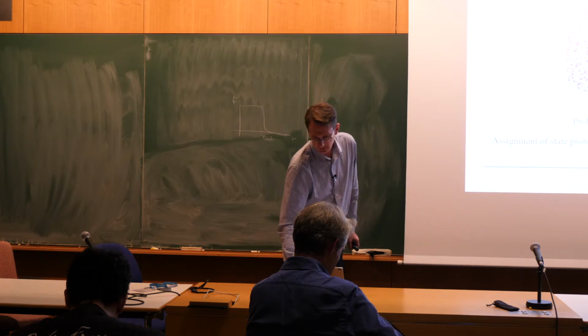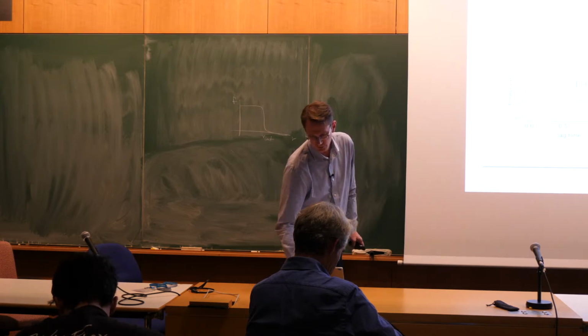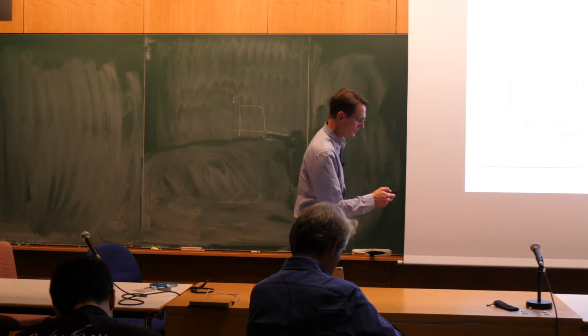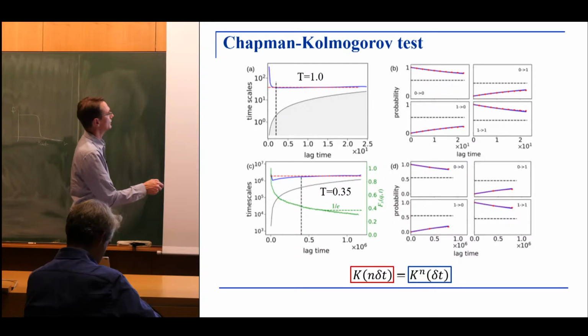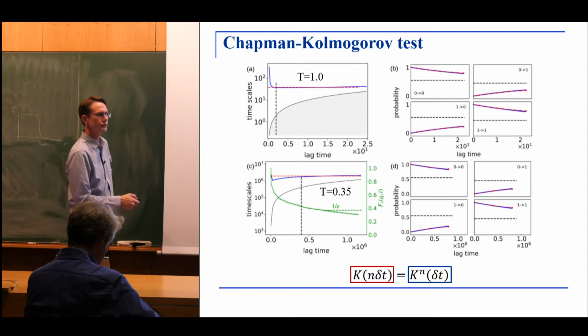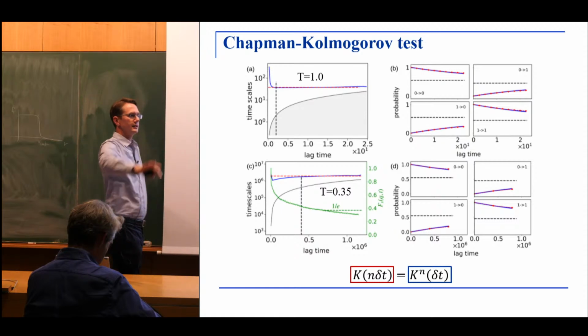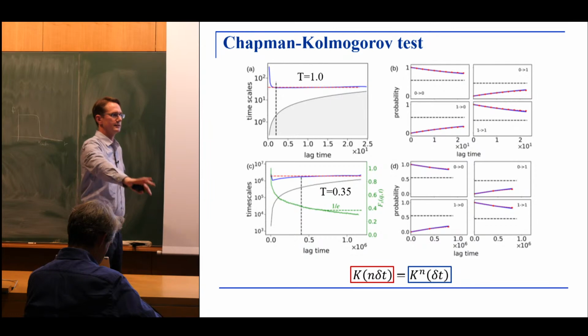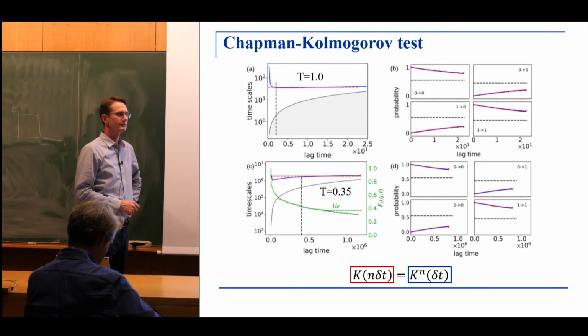In fact, you can see this here in this graph, which compares two different temperatures. One is the fluid temperature here. So 1 in these units is fluid, and you can see that the time at which you reach this plateau is essentially 1 in these units, whereas here we are in the glassy regime, and the time is many orders of magnitude larger. So yes, this lag time, of course, rises as the relaxation time of the system rises, and that is intuitive, that this should indeed happen. So that then changes.